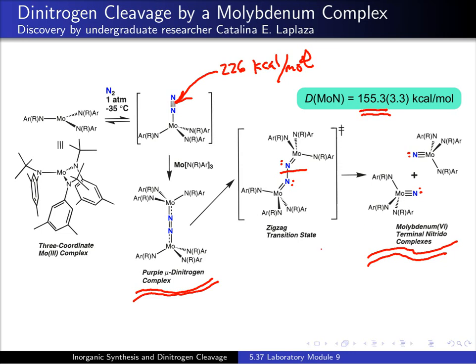So this is overall a six-electron process that utilizes the 3d electrons times two of the three-coordinate molybdenum complex to effect the complete reductive cleavage of the N2 molecule, so that the nitrido ligand is formally 3- in the product complex. The formal oxidation state of molybdenum goes from +3 to +4 to +5 to +6 in the process of splitting the N2 molecule. So let's look at some of the properties of these complexes that you'll be working with.